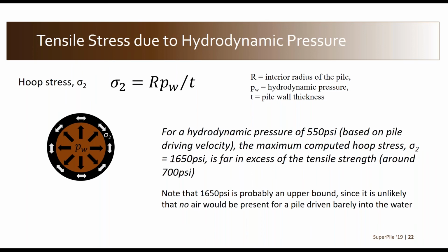And we came up with 1650 psi. So that's well in excess of the splitting tensile strength of the concrete of about 700 psi. In other words, if you struck one of these things with the hammer at the full velocity with truly zero air cushion, that would definitely be enough to rupture it.